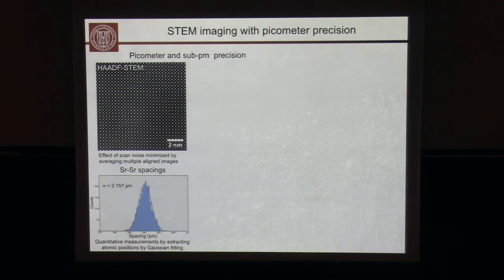And we can do that by taking a high signal to noise image, then fitting each atomic column with a Gaussian or the model that you choose, and identifying the location of that atom with high precision. We can do that to a few picometers. Here you see the strontium to strontium. This is strontium titanate, one of our favorite test objects because you can put lots of electrons on it. But this is just a test object, and what you can see is that the spatial extent of the strontium to strontium separation is just about 2 picometers. And that means we now can, with 2 picometer precision, localize our atoms in the sample and across interfaces if you want to do so.